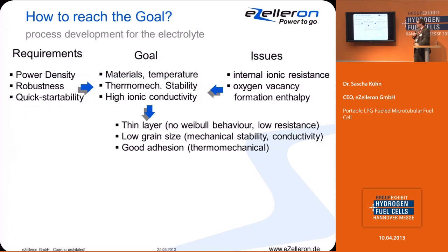This is only possible by using thin layers, because thin layers don't show the typical brittle behavior. They behave like quasi-plastic films. The behavior is more like a polymer film, not like a typical ceramic unit, with the second advantage that the thinner the layer, the higher the conductivity and the lower the resistance. So that's what you have to focus on.